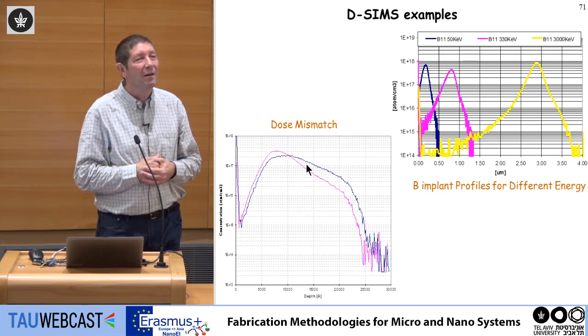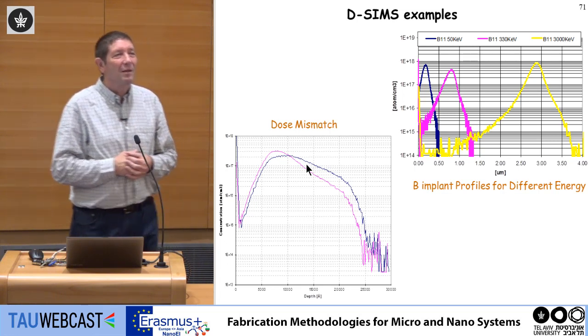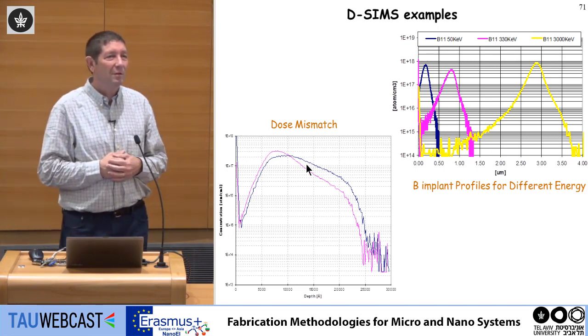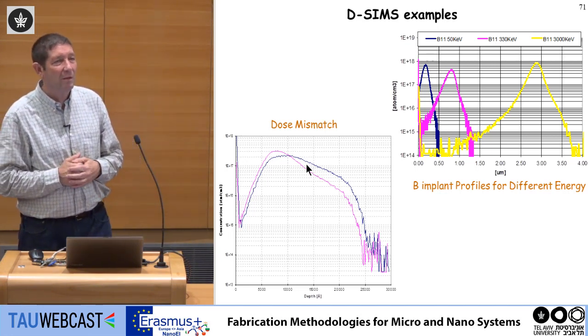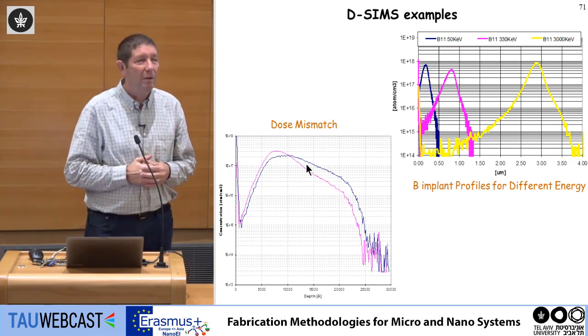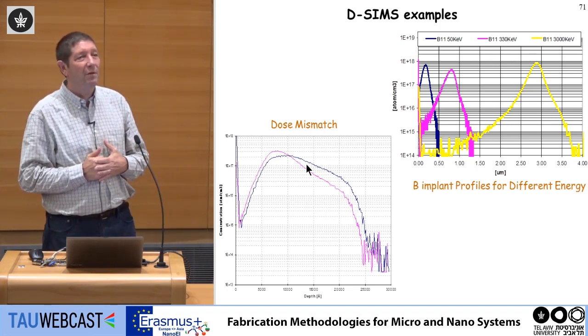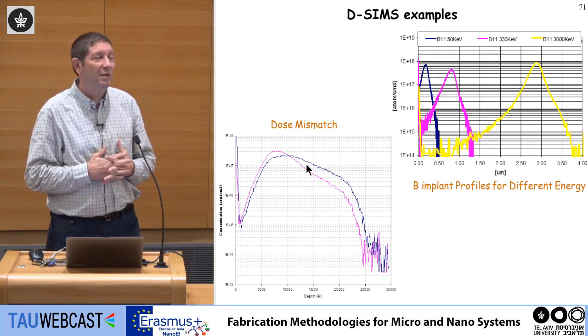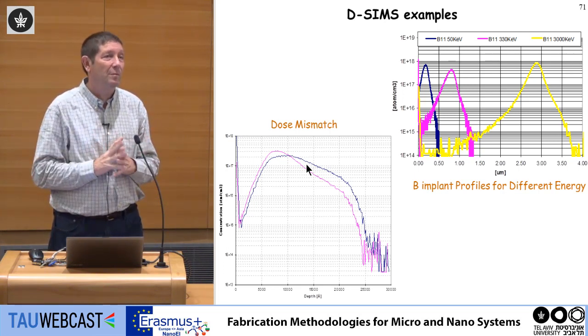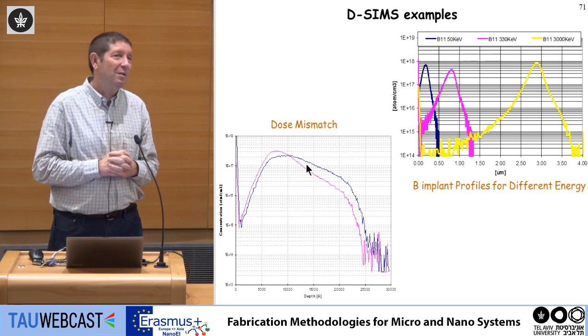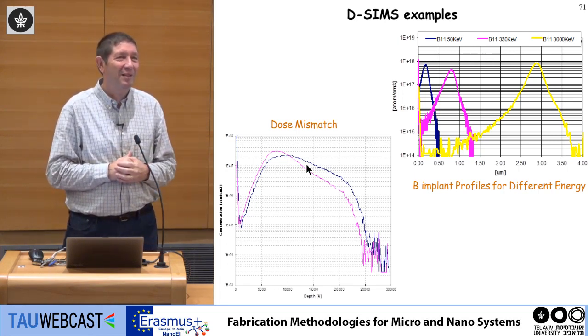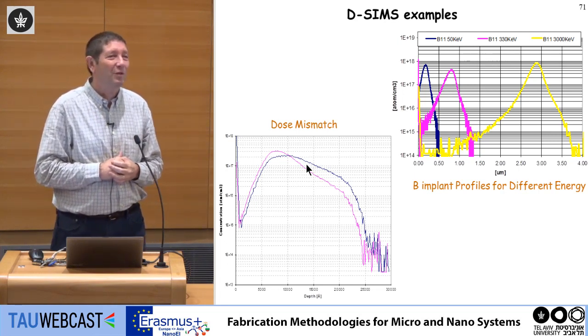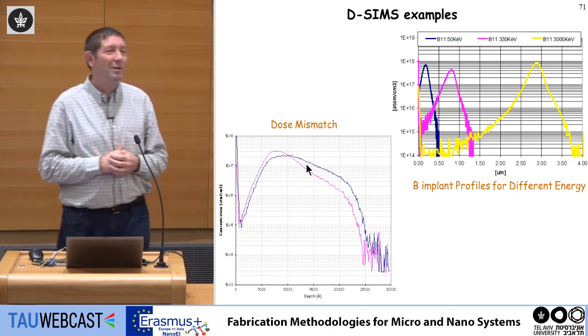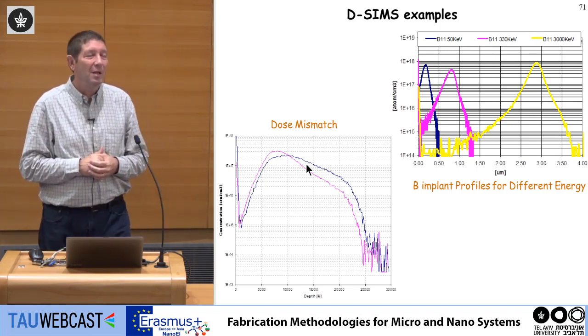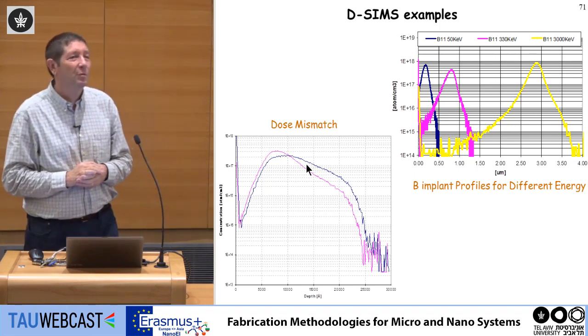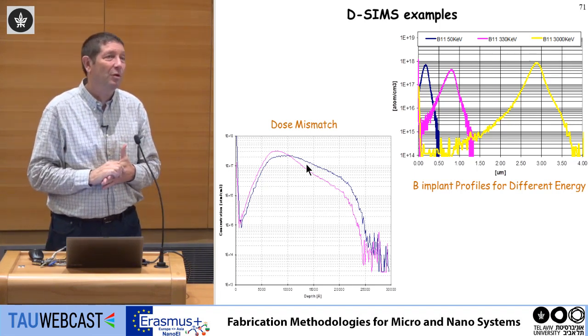What is so good about this method as opposed to the other methods? Because it's highly sensitive. The main advantage of SIMS is that I can measure doping and concentration down to the level of 10 to the 16, 10 to the 15. No other method can do it. It's destructive. You have to destroy the sample, so you cannot do it on a product wafer. You have to do it on a dummy wafer, but this technique is very important for process development, I would say, and process monitoring.